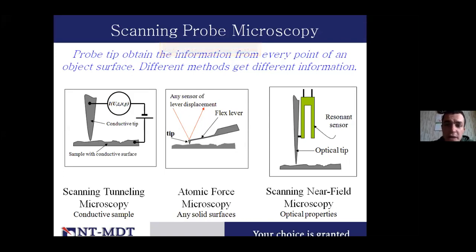In that case, we have a tuning fork and we attach a fiber to one side of the tuning fork. We control the distance between tip and sample by oscillation of the tuning fork, and at the same time we introduce laser radiation inside of the optical fiber. So we work at a very close distance to the sample, and we have an optical signal coming from the fiber, and we can analyze the reflected or transmitted signal from the surface, or through the surface in case the sample is transparent.